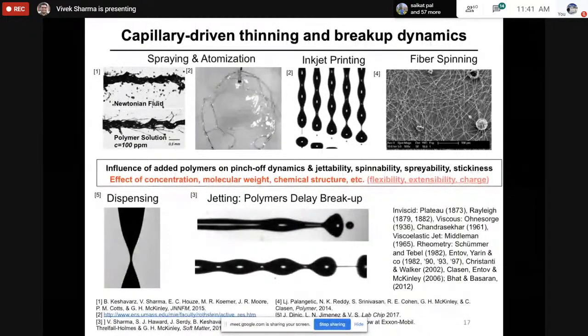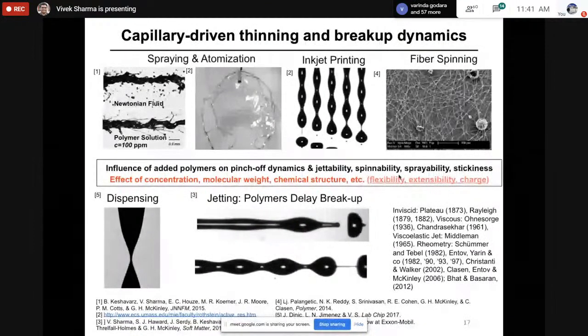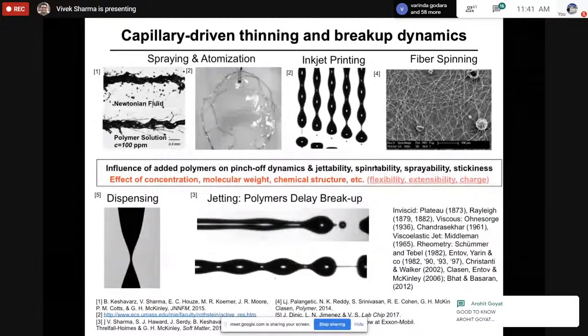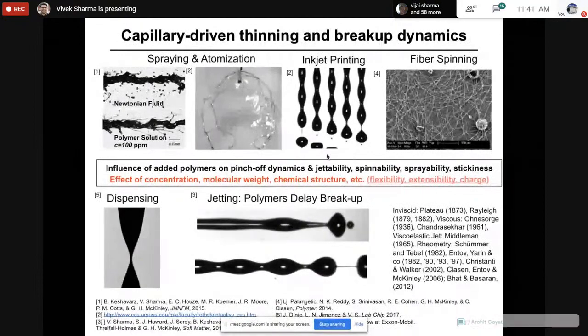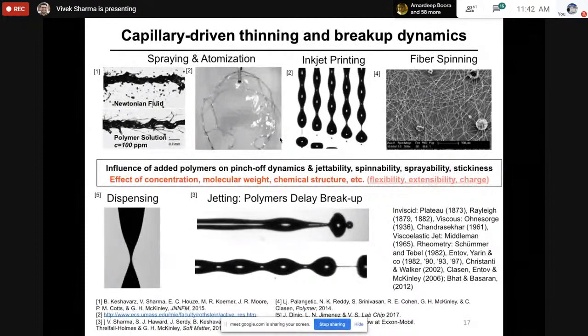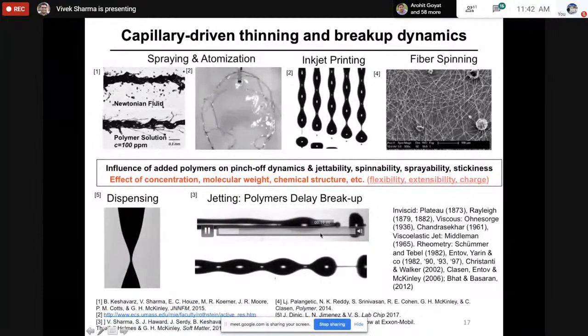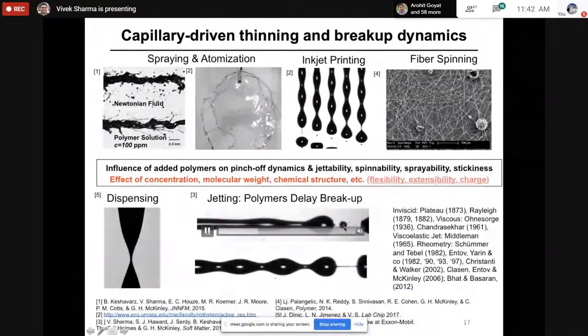Now, if I look at a liquid jet issuing out of a nozzle, and most of you have seen a liquid jet every time you turn a tap on, what you can visualize if you had access to a high-speed camera, or in this case, I use strobe imaging that allows a time resolution of a microsecond. Here is a water jet, and as this water jet issues out of a nozzle, eventually surface tension-driven instabilities arise, which cause the neck to have the sinusoidal instability that results in formation of droplets. You can see very nicely there's a satellite droplet forms, there's a large primary droplet forms, and as you examine this movie, you might also see that before pinch off, there's a very nice cone that forms, and that cone converts into the satellite drop.